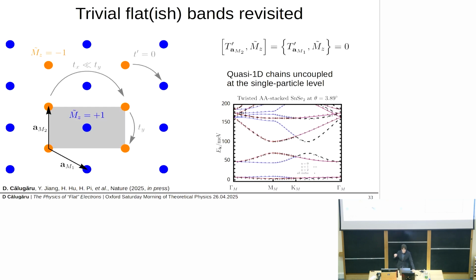Essentially, after you go through all these maths, you are able to show that these flat bands in twisted tin selenide, right, they have a very interesting quasi-one-dimensional property. So even though the system is two-dimensional, it's actually made up of one-dimensional chains. Electrons cannot hop between chains, right? But they still interact electrostatically between chains. So this actually paves the road to, for example, realizing something called the Luttinger liquid, right? And really studying low-dimensional physics in real experiments.